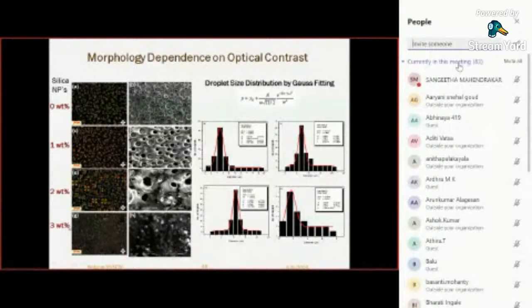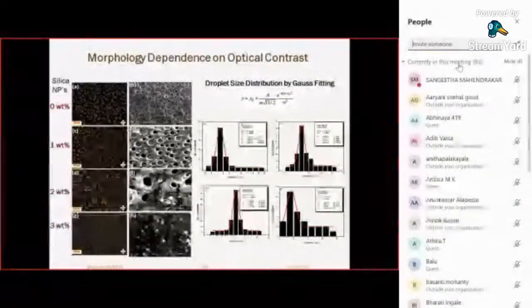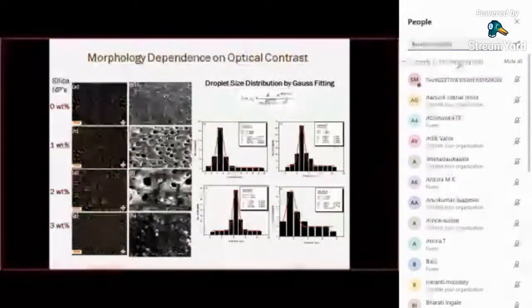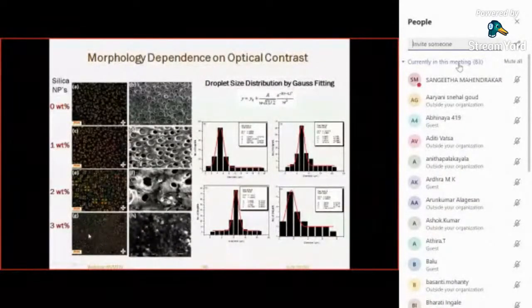But when the concentration reaches 3 weight percent, the silica nanoparticles get segregated with the polymer matrix, and here some segregation is there which decreases the contrast. That means we are getting a poor response at 3 weight percent. So we have studied this series, and the result has been published in the Liquid Crystals journal.